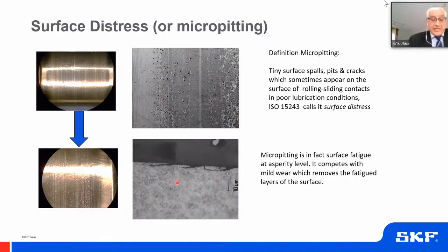It's important to say that although this is basically due to poor lubrication conditions and fatigue at asperity level, there is always a competition between fatigue and wear, mild wear, the kind of wear that modifies the topography only. If you have too much wear, you may not see surface distress. If you don't have any wear, you may see surface distress very quickly because you don't have enough flattening of the topography.